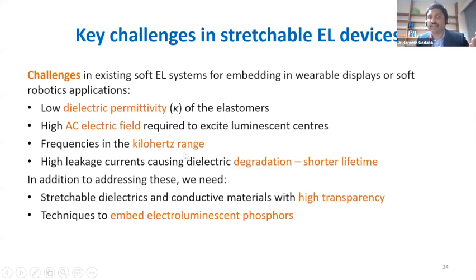So we need a kilohertz range AC signal, which is again also of a high voltage. And high leakage currents can also cause dielectric degradation. If there are high leakage currents, this can also cause heat in the elastomer, which can cause it to break down.